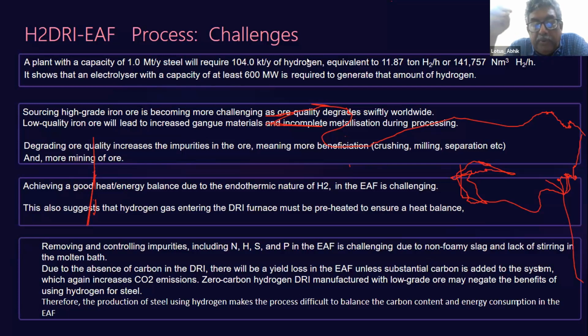So zero carbon hydrogen DRI manufactured with low grade ore may negate the benefit of using hydrogen. Therefore, the production of steel using hydrogen makes the process difficult to balance the carbon content and energy consumption. Okay. So hydrogen is good for not emitting carbon dioxide. That is true. And hydrogen is a very good reducing agent. Its reducing efficiency is better than carbon itself in many cases.